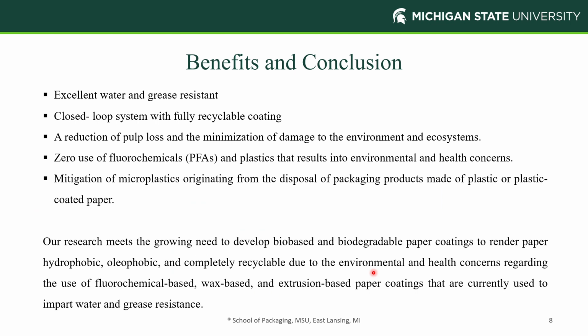So in order to conclude, we have generated a coated paper that produces good water and grease resistance, and it's a completely closed loop system, starting with the coated paper, washing the coating off and reusing the pulp, which also reduces the loss of pulp and saves the environment. We also use no fluorochemicals that are harmful for the environment and the health of humans. And we also mitigate the formation of microplastics because our paper does not contain any plastics in the first place, and there's no risk associated with landfilling and dumping of the plastic and paper waste.